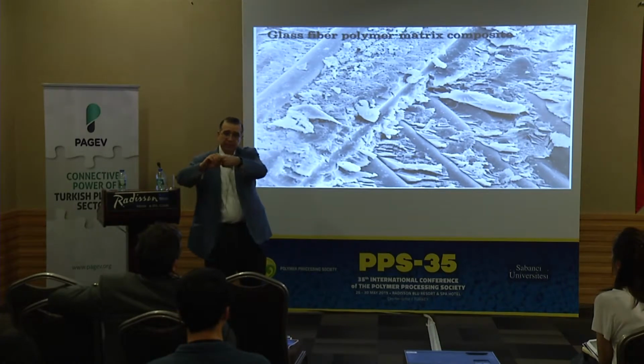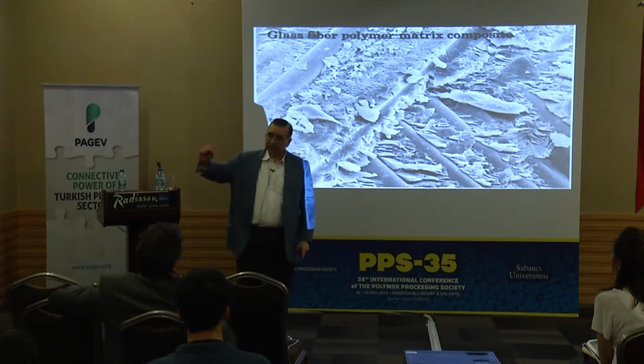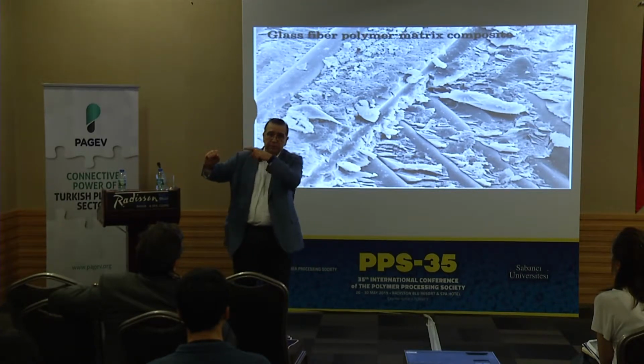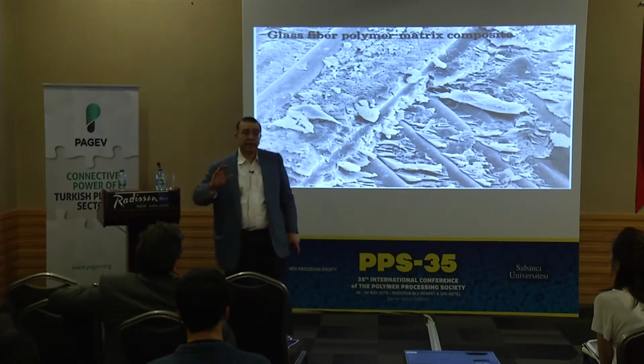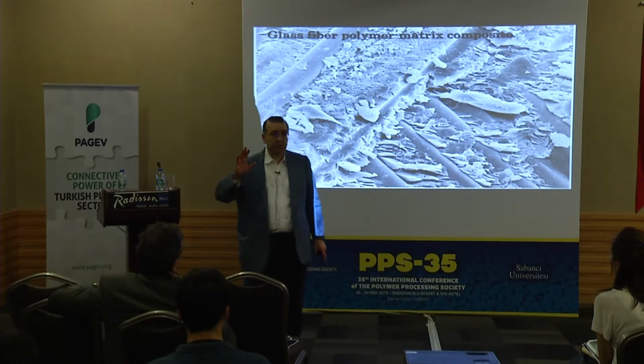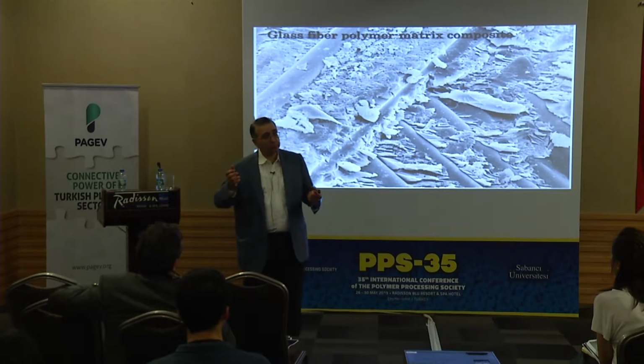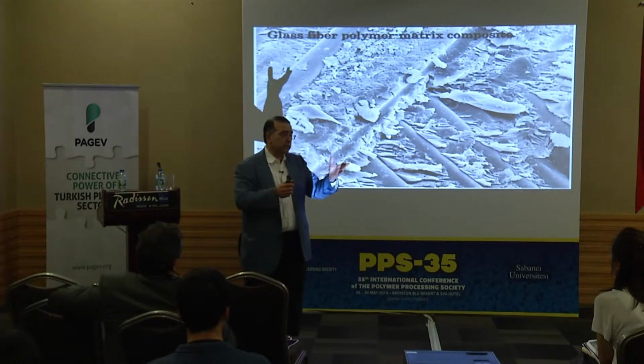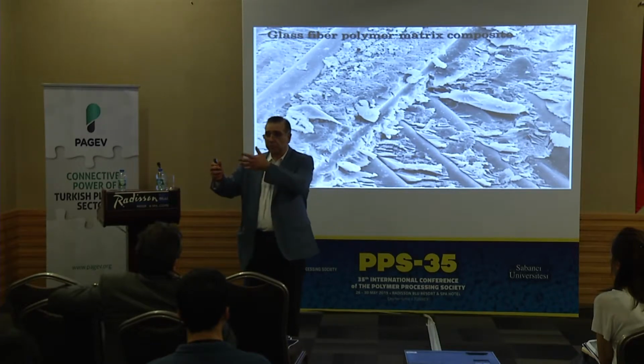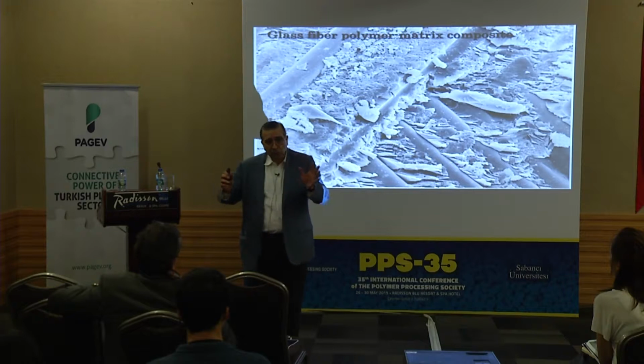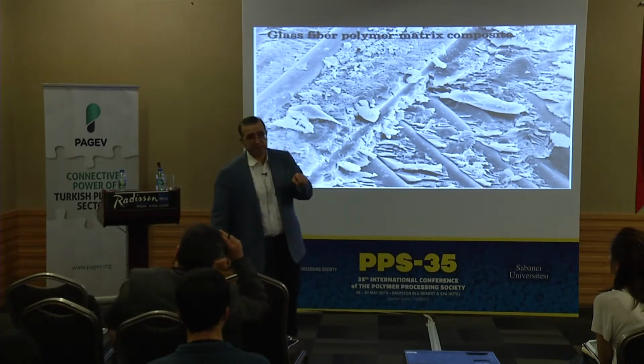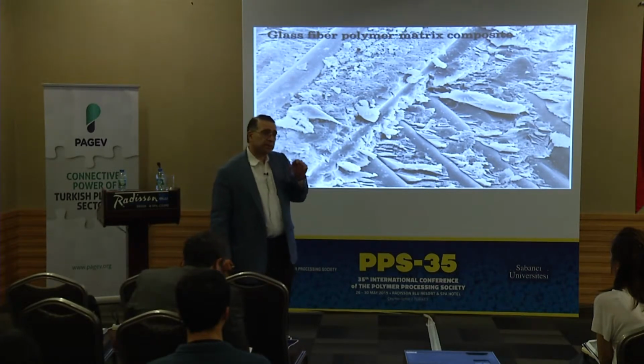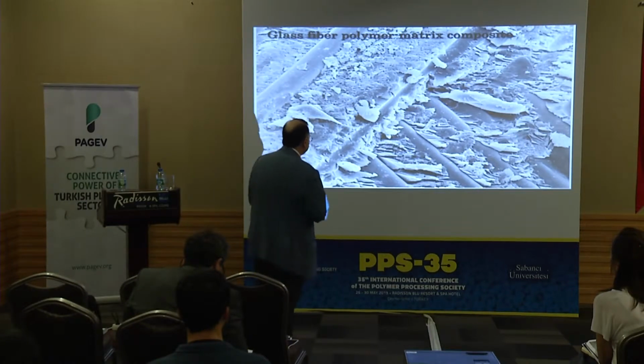If the fiber is pulled out, and in the fracture surface you see a bunch of holes in the resin, it means that you do not have good interfacial properties. You do not have good interfacial bonding. So if you make a composite part, break it, look under the microscope, and on one side you have a bunch of fibers, on the other side you have a bunch of holes in the resin, your composite is not good. You will not really get benefit from the presence of fibers. So you have to deal with the sizing and the surface chemistry.